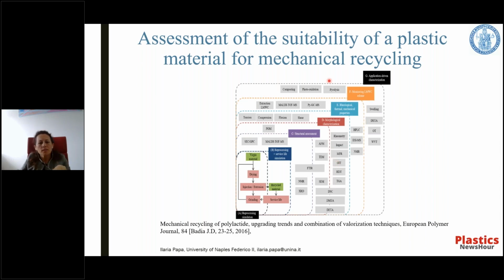Among all these possible alternatives, one of the most important is certainly the mechanical recycling, which makes it possible to recover waste PLA and reuse it as a raw material in forming processes in order to obtain new products. One of the main problems of this process is the inevitable thermomechanical degradation to which the material is subjected due to the conditions to which it is subjected during the life cycle and during the recycling. This degradation causes the mechanical, thermal, and rheological properties of the recycled material to be different from those shown by the virgin or neat material, and often making it impossible to use the recycled material for the same application for which the virgin one was used.